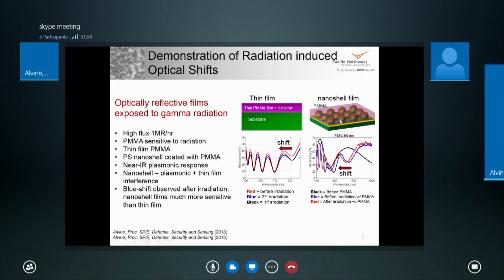So this can be used as an optical dosimetry, and that's very important because you're basically only looking at the reflection of the film. In a case like Fukushima, you really don't necessarily want to be right up next to the source, or the place where you're trying to see how radioactive it is. You can look at this from a standoff method, in a case where the fluence is quite high.